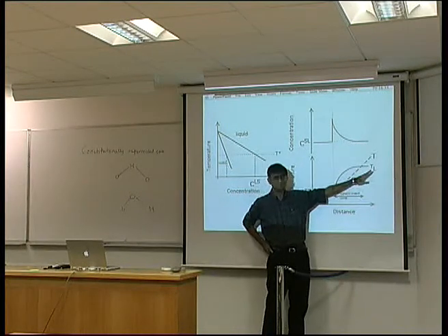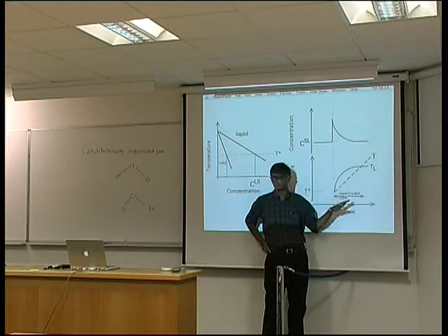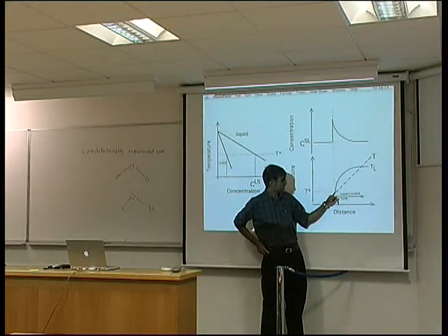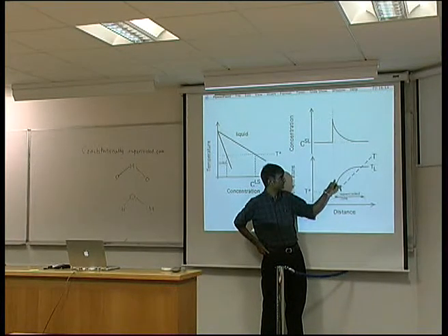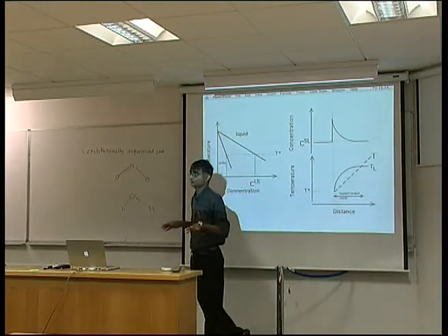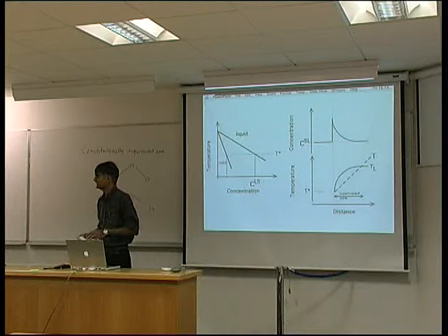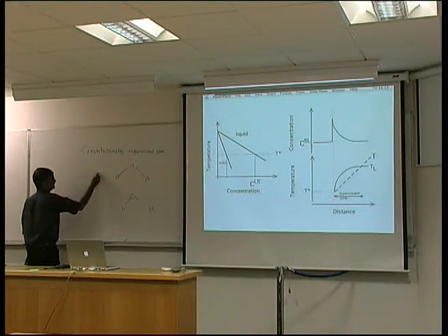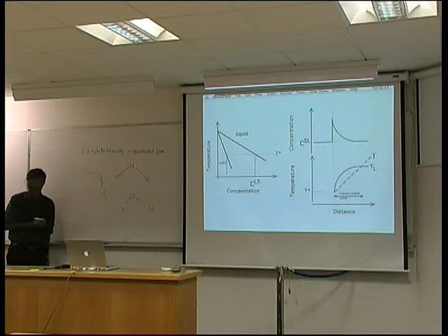That means if this actual temperature gradient is gentler, then I will have a larger supercooled zone. And if the gradient of the temperature is greater than the gradient of the liquidus temperature here, then I will not get dendritic solidification. And somewhere in between, I get what's known as cellular solidification, where the dendrites try to develop, but the supercooled zone is really quite small. So you get a structure like this instead of a branching structure. I might have a movie to show that.